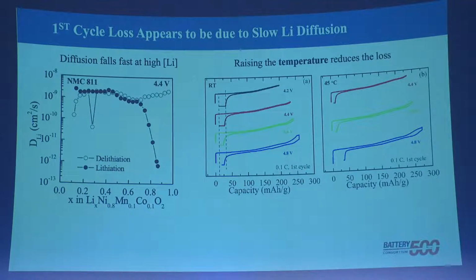So we've been looking at, can we modify the materials? But first, to double check that this wasn't really the case, we looked at these materials at 2 different temperatures, room temperature and 45 degrees, and at a series of different charging voltages. Clearly, the higher the voltage we go to, the more lithium we take out, so the more capacity we get. Then when we discharge it, what we do is keep within voltage regimes.